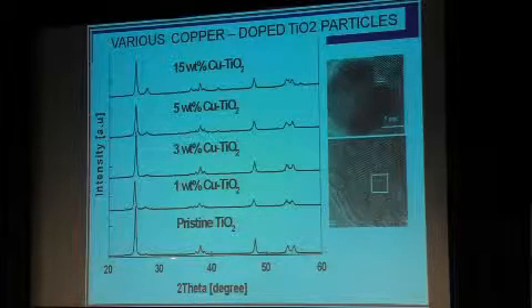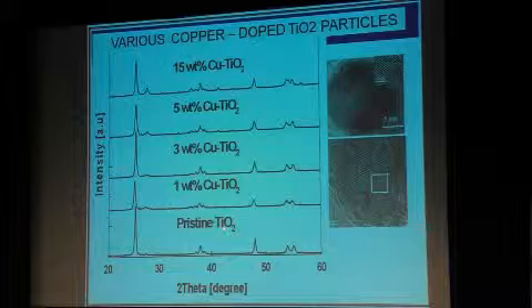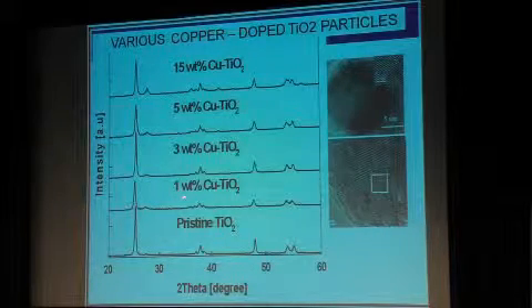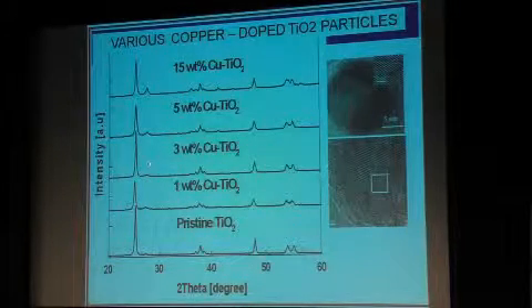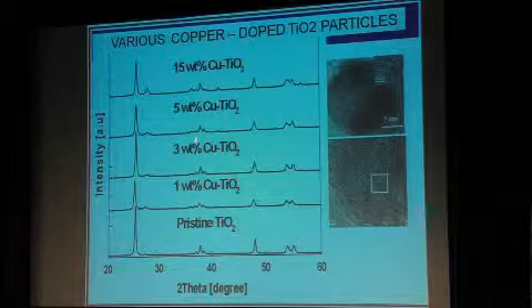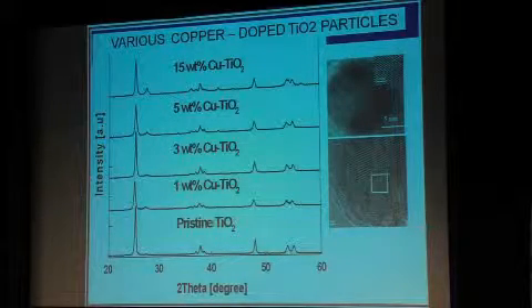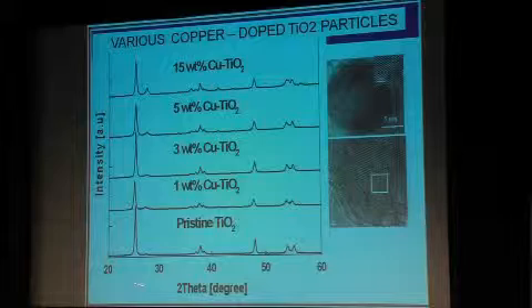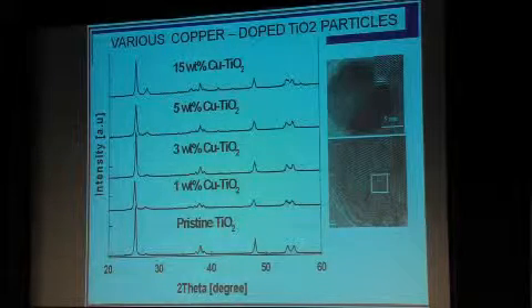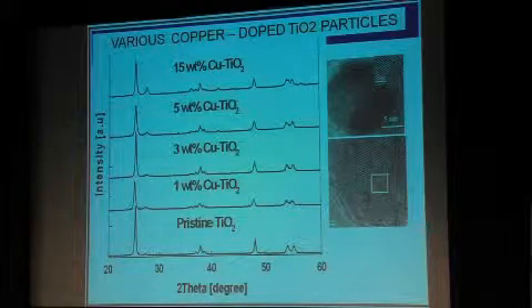Under these conditions, of course, we make pristine anatase TiO2. I begin to add copper. You can see that the rutile phase begins to appear. So one has to keep that in mind when one looks at activities and so forth. But these are very precise samples which can now again be put to functional use or toxicological tests and so forth.